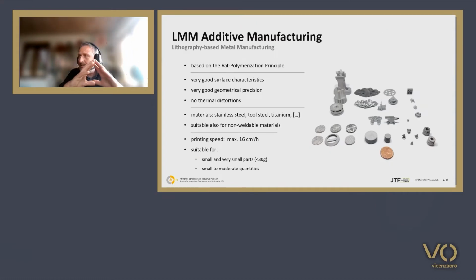And in that framework, we developed a completely new additive manufacturing process, which is based on lithography. And Dr. Klotz already said that with laser powder bed fusion, there are a couple of issues that have to be solved. One is the heat dissipation. The second is that you always need support structures, which have to be removed afterwards. There is also the very inconsistent heat distribution: you're very hot where the laser is, but should be cold where the powder is that's not to be fused. You also have thermal stresses, and this also leads to a lot of after-treatment and rework that has to be done. And the process we developed